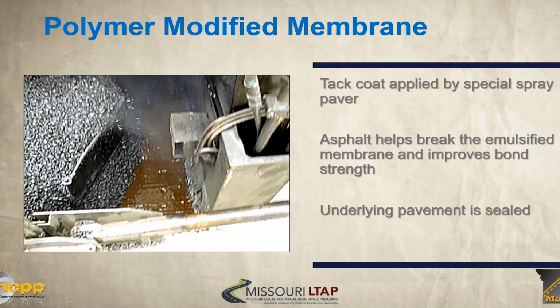So here's where the asphalt is being placed onto the mat, and then you have the screed back here. But right in front of that is a spray bar, which is variable width, and it's spray applying this polymer modified tack coat. So in essence, that's where the preservation comes in, it's sealing the existing pavement. This would be akin almost to a rubber membrane interlayer, for instance. And so this hot asphalt helps break the emulsion very quickly, and it improves the bond strength.